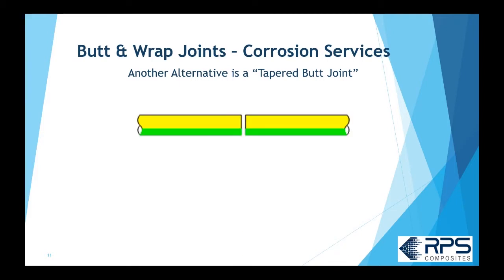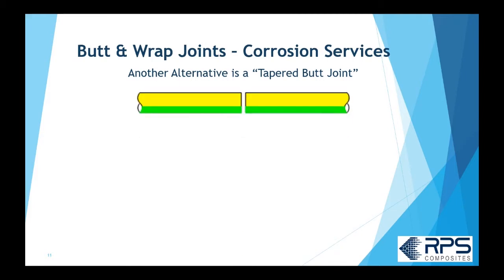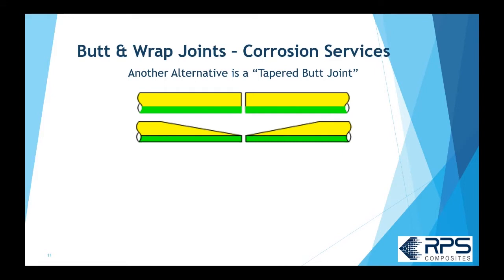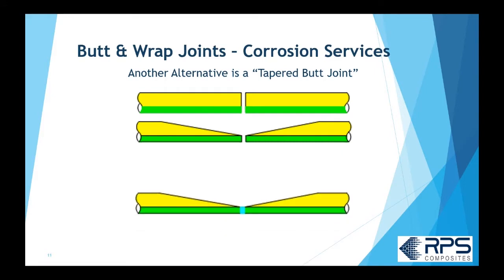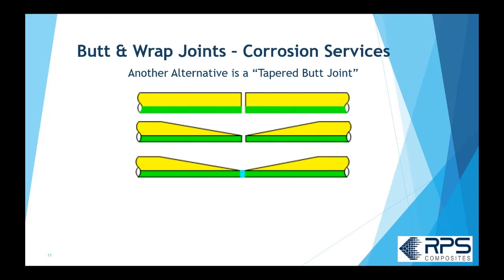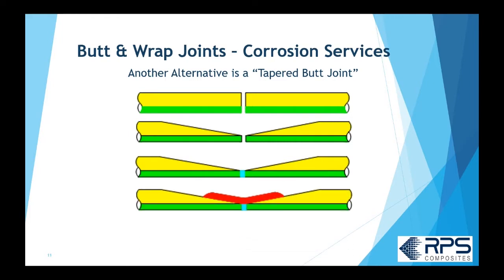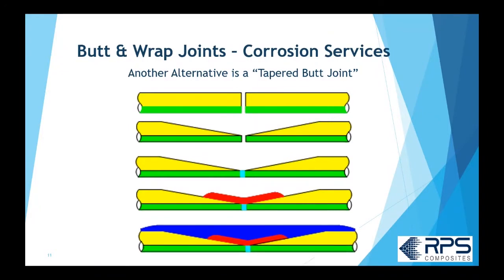The other way is to use a tapered butt joint. So I start off the same way. I have my two pieces of pipe that are sanded and I grind down right to the corrosion barrier. I put in my small amount of crevice paste this time. And now I put some of that corrosion barrier material between the seams, between the joint line. And essentially I have a continuous corrosion barrier. And now I laminate on top of that.